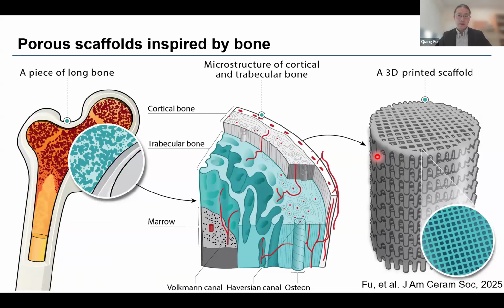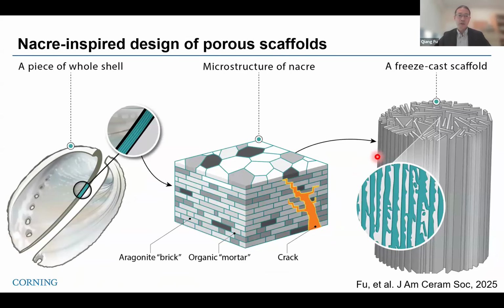To improve the strength even higher, we try to learn from biological materials. One good example is nacre. It's made of a brick and mortar structure, which gives it very high strength and high toughness. In this case, we used a freeze casting method to produce this laminar type structure, which produces very high strength when you test along this orientation. That gives us hope for a very high strength and tough material for bone regeneration.